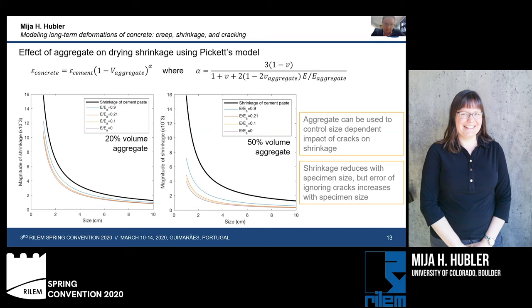Now, if we add 20% by volume aggregate or 50% by volume aggregate, you see that this dark line, which represents the magnitude of the shrinkage as a function of the size, becomes reduced. So the aggregate helps us to resist this shrinking of our material with its stiff inclusions. And so if we adjust the stiffness of the aggregate, we see this effect is increasing.